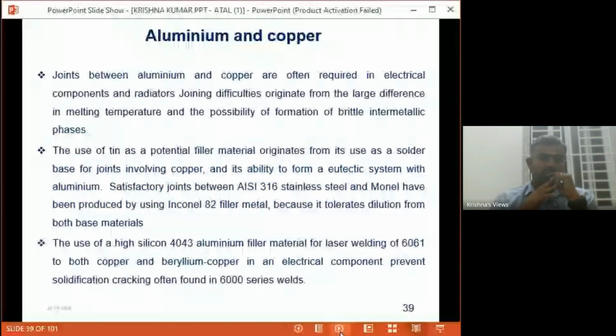Satisfactory joints between 316 stainless steel and Monel have been produced by using Inconel 82 fillers, which tolerate dilution from both materials. The use of high silicon 4043 aluminum filler material for laser welding of aluminum and copper, and beryllium copper in an electrical component, prevents solidification cracking often found in 6000 series welds.